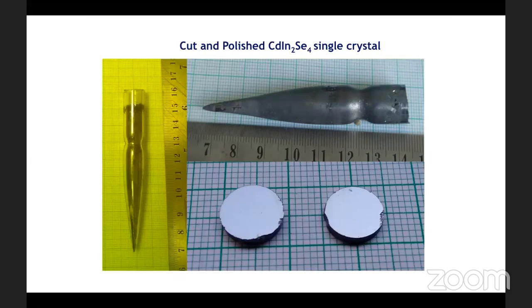We have many furnaces, so that we have grown many crystals by the Bridgman technique. You can see here the crystal starts at the bottom tip, because you need a single orientation. That's why you make a very sharp crucible. This is the cadmium indium selenide material we have grown in my lab in India.